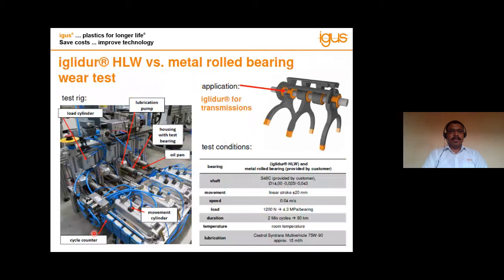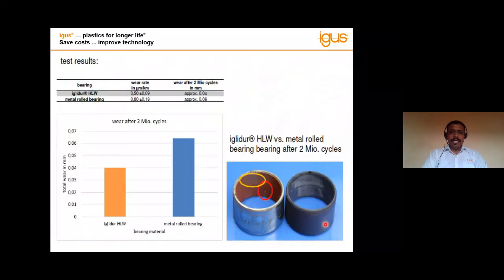One more case study of iglidur HLW material versus metal rolled bearing. This wear test we conducted for a special linear stroke of plus minus 20 mm at a speed of 0.04 meter per second, load 1200 Newton, roughly 4.3 megapascal per bearing, and we tested it for 2 million cycles. When we convert it into linear travel, it is around 80 kilometers. We can see the wear results in the upcoming slide.